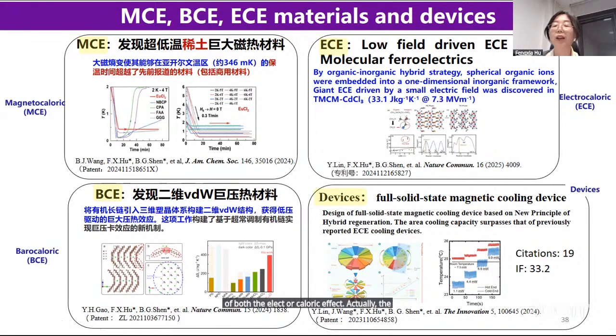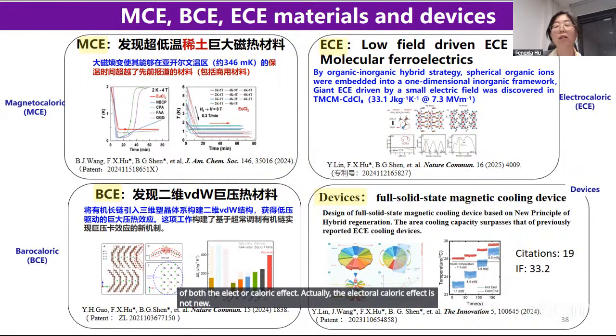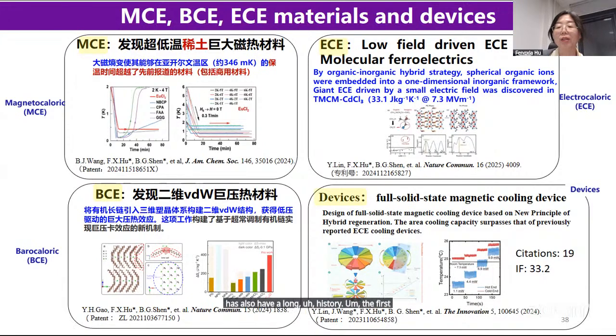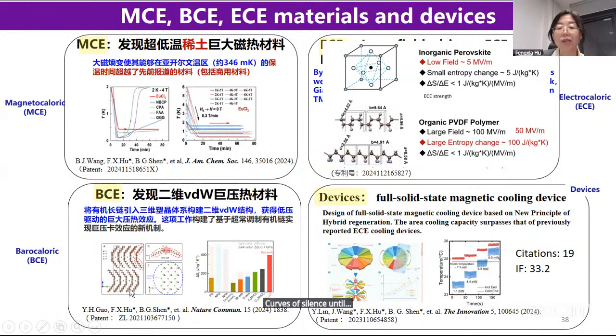Actually, the electrocaloric effect is not new, it also has a long history. The first appearance of this word was about the 1940s, but the area of the electrocaloric effect kept silent until the discovery of the giant electrocaloric effect in the PVDF polymer. This material shows a very huge entropy change, but the driving field is also huge. For the inorganic perovskite materials, the driving field can be small, but the entropy change is also small.